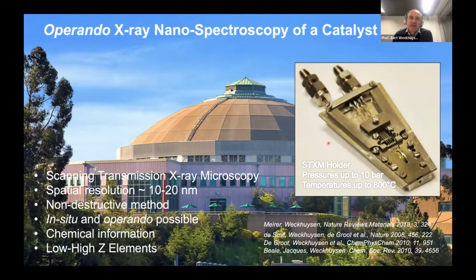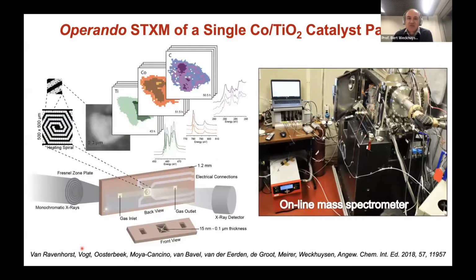That also means we have been developing different cells to make that possible. The advantage of soft X-rays is that you can measure a kind of XPS spectrum. Hence, you can measure low and high Z elements together. So that means you can measure a cobalt titania catalyst while CO is hydrogenated. You can measure not only the titania and the cobalt via the spectrum, but also the carbon. So you can measure organic and inorganic while the reaction is happening.